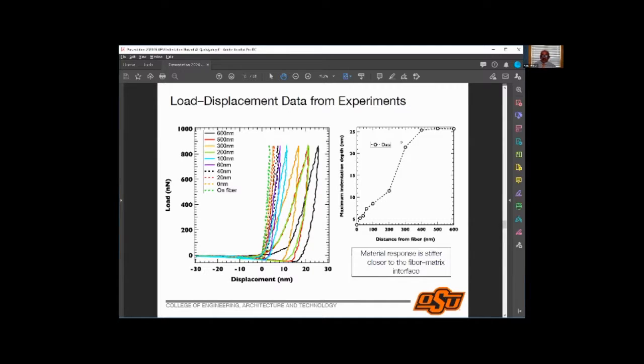So to answer your first question, will the presence of, for example, hygrothermal or moisture absorption play a role? We believe it will. The reason we believe it will play a role is because physically the interface is different than the bulk matrix. That means chemically it has to be different. And if it is chemically different, for example if the cross-linking densities are higher, then the response to UV, and not so much UV, water vapor is a bigger concern. The effect of water vapor will be very high. By the way, the reason why we study UV and not water vapor here is because UV is easier to study. If you take a composite laminate, and you look at the cross section, and you have the carbon fiber, the interface and the matrix, and you subject it to moisture absorption, we get moisture induced swelling.